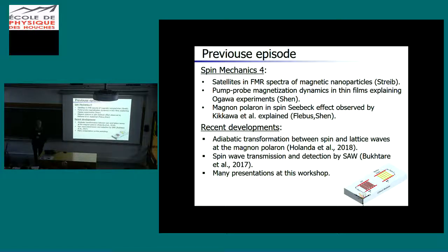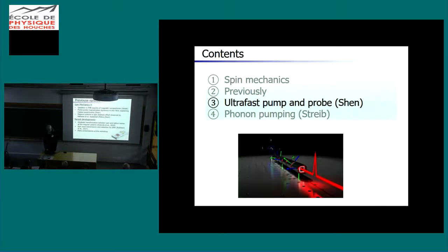Now there are many more recent developments as well. Let me just mention these ones here from the Resende group, which in an inhomogeneous magnetic field could transform a magnon into a phonon at this magnon-polaron crossing. There is an interesting experiment by the Tulapurkar group, which showed reciprocity of phonon-magnon conversion in such a structure. And of course, there will be many interesting presentations still at this conference and posters as well.